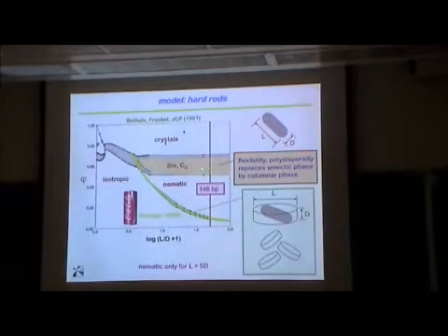You actually get a columnar phase because of the polydispersity in length. It makes it preferential for these columns to stack up on one another rather than go into layers. If you have polydispersity in length, then you lose the translational entropy gain from getting next to each other, because the rods penetrate into adjacent layers and sort of latch things up. Okay, so this is where we expect the nucleosomal DNA to be.